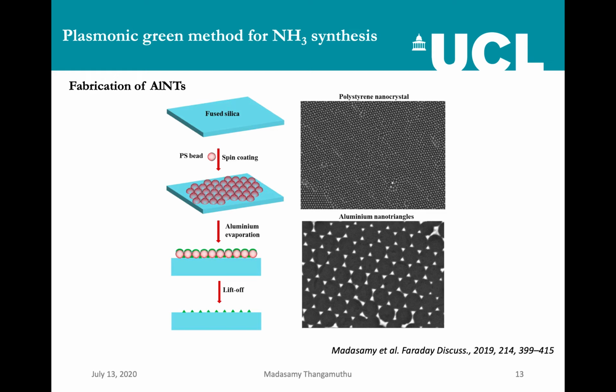When we shine a light on these metals, the conduction band electrons oscillate in resonance to the wavelength of the incident light, and after some time, this resonance oscillation releases the energy. Once the resonance is stopped, it releases the energy, and that energy excites the electron above the Fermi level, and this electron can be used as a plasmonic hot electron for breaking any adsorbate molecule. At the same time, this kind of oscillation also generates an electric field on the surface of the metal, and this electric field, if we attach it to a semiconducting surface, can improve the huge number of charge carrier generation inside the semiconducting material. So that's how the plasmonic method works.